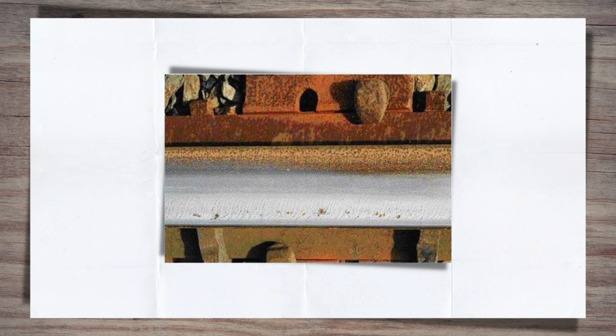This stress causes cracks on the rail surface that grow due to the repeated cycle of passing wheels. The cracks can either grow across the surface of the rail, leading to shelling or spalling defects where the material appears to flake off, or they can grow down into the rail head, known as a transverse crack. If left, these transverse cracks can lead to sections of rail breaking away, or the rail breaking completely.